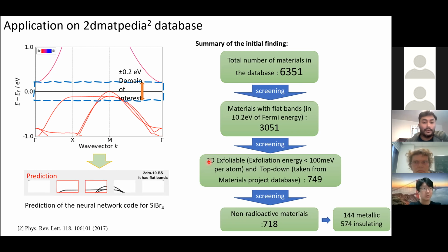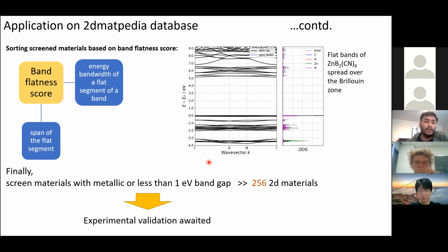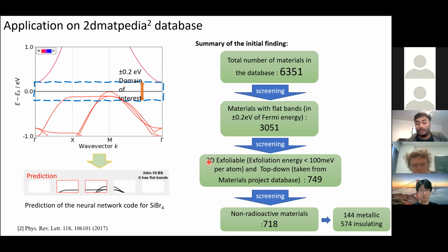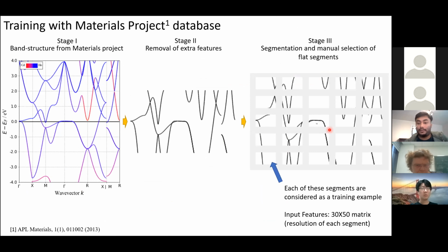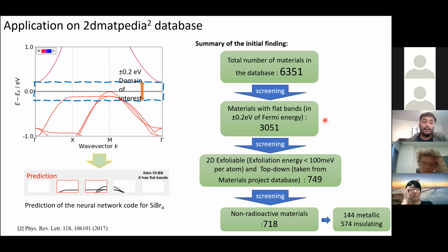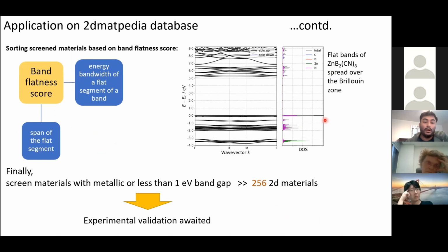So once we have approximately 700 materials, we still wanted to narrow down our search, and we introduced a band flatness score. The band flatness score had two attributes. First is the energy bandwidth of a flat segment, whether a segment that is passing as a flat band is very flat or has some waviness in it. And the other attribute is how spread the flat band is in the Brillouin zone, whether it is spread throughout the Brillouin zone or only a very small part of it.